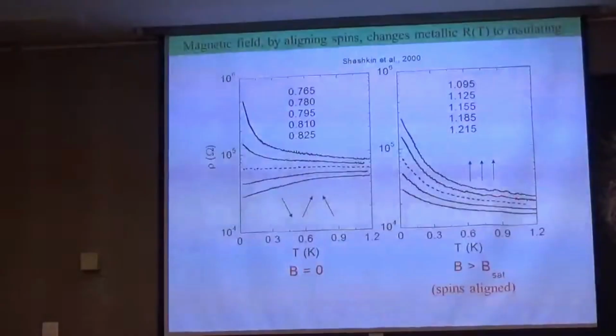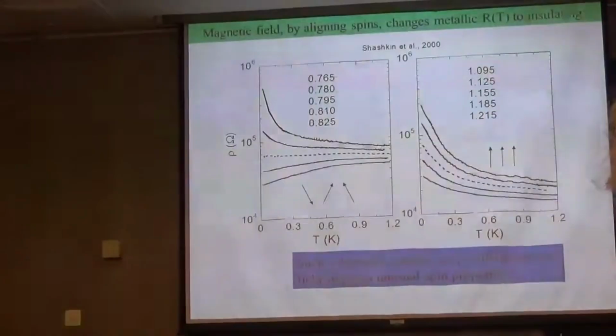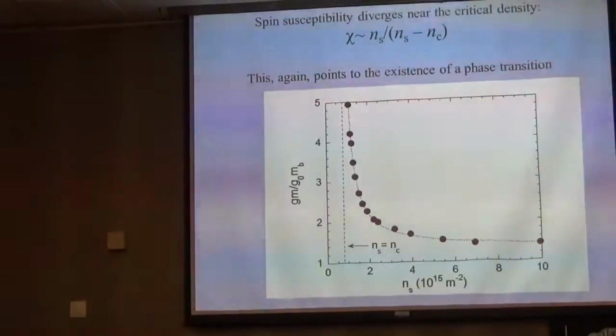But the magnetic field does more than that. It not only increases the resistance, it also completely wipes out this critical behavior. You see? It looks like by applying a magnetic field we came back to the normal situation, to what we're supposed to see. When spins are aligned, the system behaves like an insulator. So it suggests some unusual spin properties. Somehow spins are behind this problem. Indeed, we measured the spin susceptibility. Here it's shown: g factor times m, where m is effective mass, but you can just think of this as the spin susceptibility. And as a function of electron density, it follows this critical form, and it diverges at exactly the point where we see the transition from insulator to metal.